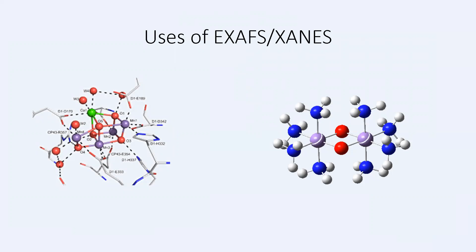The XANES region, closer to the edge, depends on multiple scattering events of the emitted photoelectrons with nearby atoms. As such, XANES provides detailed information about the local geometry of the absorbing and neighboring atoms. Such methods can be used to probe the coordination of the sample's atoms.